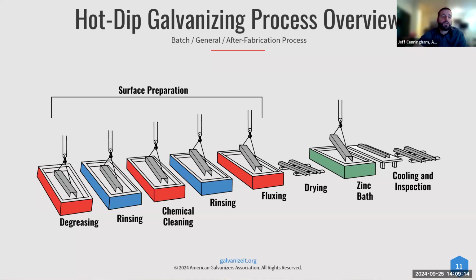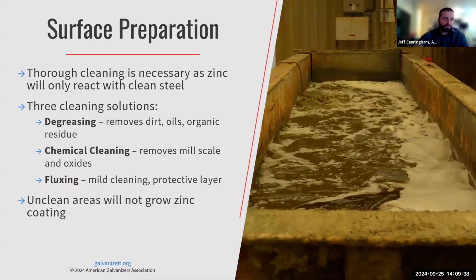It goes through a degreaser for dirt, oils, that sort of thing. Chemical cleaning is a little bit harsher. It removes mill scale and oxides. And then the last part is fluxing. The flux tank actually does two things. It cleans off anything that the chemical cleaning and degreasing didn't, and it also puts on a protective layer around the steel. So while it's drying, it won't pick up anything before it goes into that zinc bath. And then it's cooled and inspected.